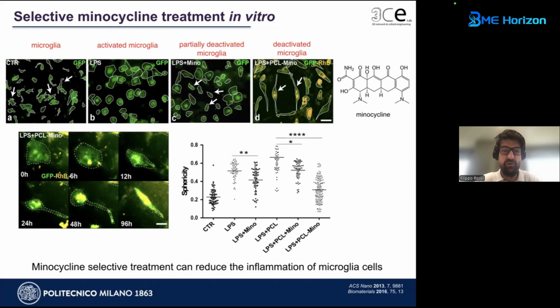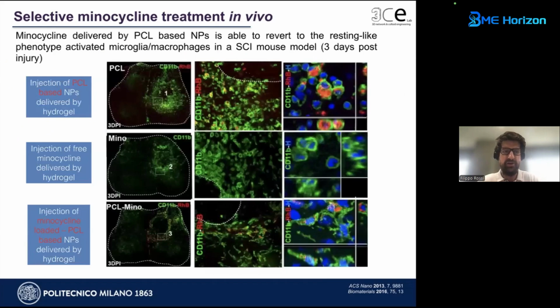You can see the groups visible here. The control groups are microglia itself and LPS, so microglia activated. You can see the round shape typical of activated microglia. Then the two other groups are the treated groups. LPS plus mino is the group where the LPS cells were treated with minocycline itself without nanocarrier, while in the other you can see the LPS with nanoparticle, so minocycline loaded within nanocarrier. You can see that this selective treatment can reduce the inflammation more effectively, and in the time-lapse analysis the cells are able to go from a round-shaped structure to a spindle-shaped structure.